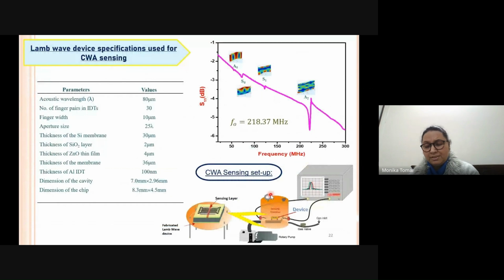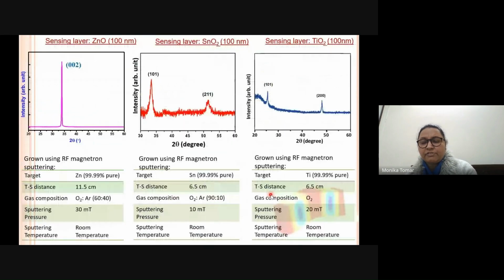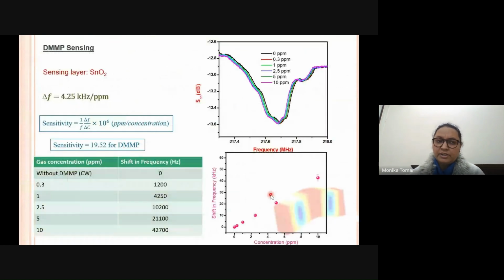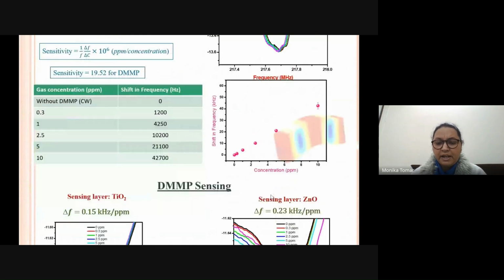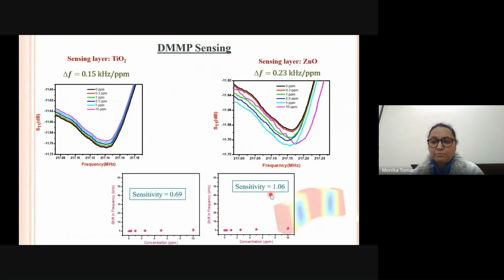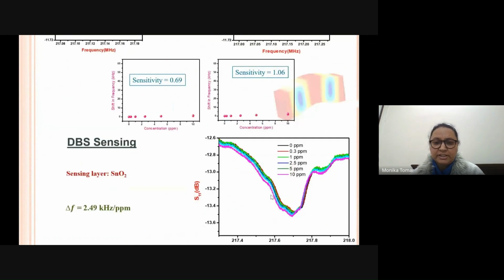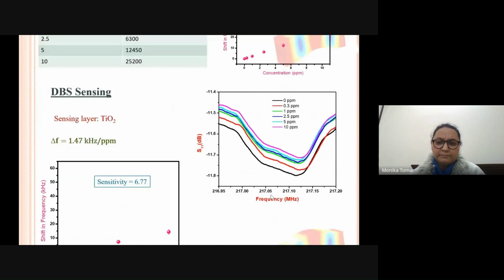Then the main aim was the detection of chemical warfare agents. We utilized these devices for detection of chemical warfare agents. We had chosen 3 sensing layers: zinc oxide, tin oxide, and titanium dioxide. We utilized them for DMMP and DBS. These are the two simulants for the chemical warfare agents. All of them showed some sensitivity.